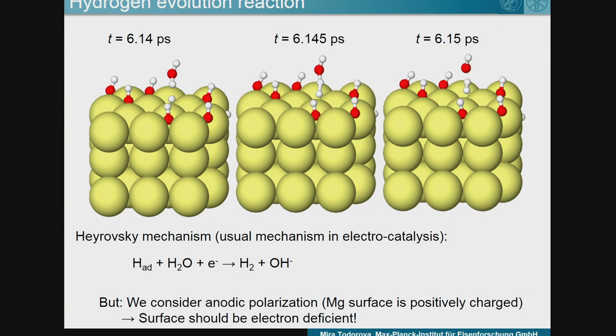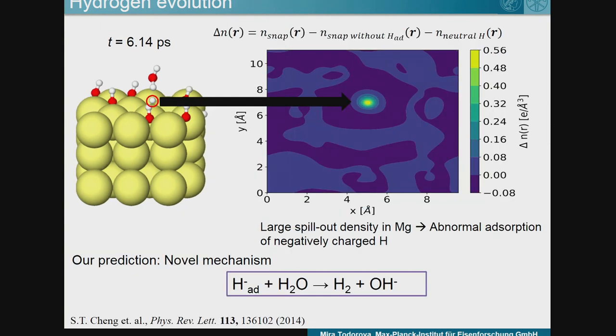Now, this is a reaction that is known, however, for a situation where we do have cathodic conditions, where there is a surplus of electrons at the surface. Now here we are at electron deficient conditions because the magnesium is positive. So where does this electron come from? What we did is to look at the difference density of a surface without hydrogen, with the neutral hydrogen and just the overall, and what we find is that hydrogen on this magnesium surface is negatively charged. So we don't have an additional electron that is coming somehow from the substrate, but actually the adsorbed hydrogen is slightly negatively charged, and the reaction we have is this one here.